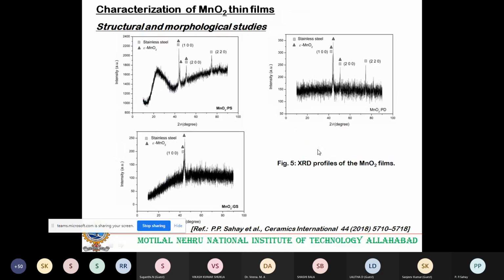Now, once you deposit any film for any device application, first we have to characterize the film, to see whether our film has been prepared or not. Not only in the supercapacitor, but in other cases also. The very popular technique is to do the XRD, and we compare the XRD profile with the standard JCPDS database. When it matches, we say that our film is prepared. But in some cases, we find that the peak is not very clear. Then we have to move towards other techniques in addition to the XRD, that is FTIR and Raman.